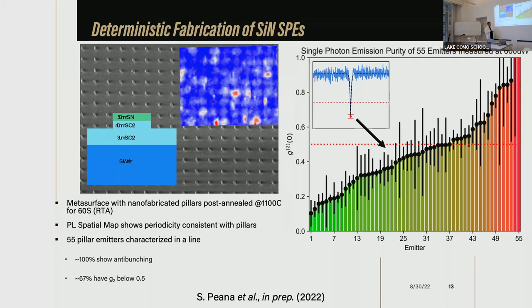And 67% have G2 below 0.5, indicating that they are single photon sources. Why is it important that this number is 67? Because normally people prepare single photon sources statistically by using annealing or ion bombarding, and in that case it's controlled naturally by a Poissonian process, which gives you 35% to obtain a single photon source. Others would be either no photons or more than one photon. Here, right away we got 67, which clearly shows it's not random, it's not statistical.